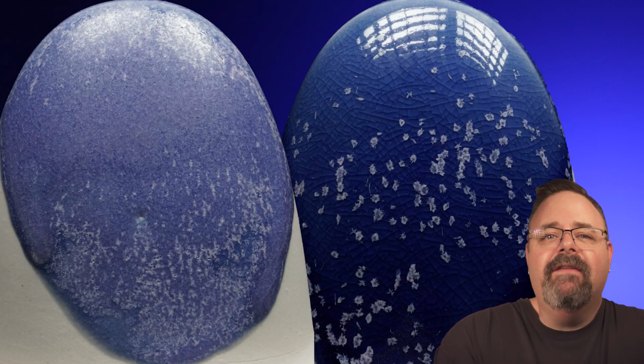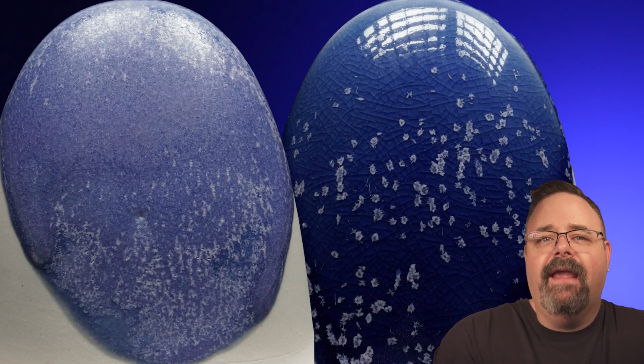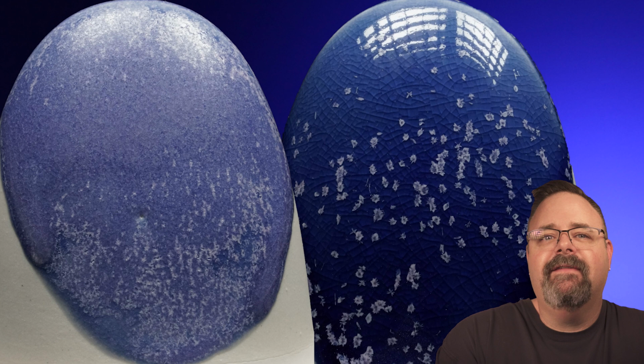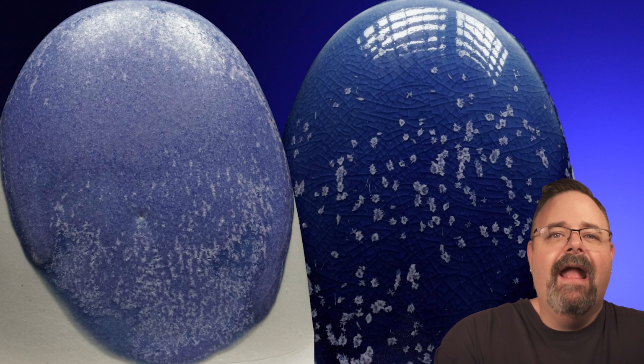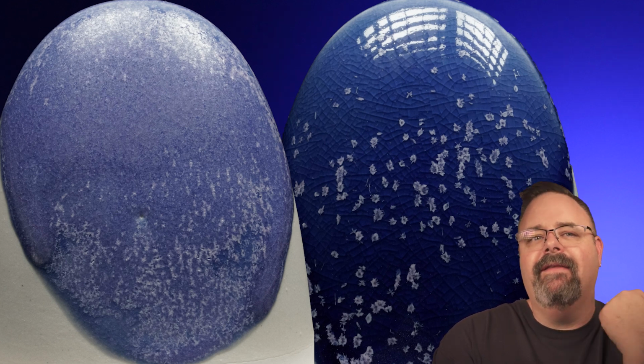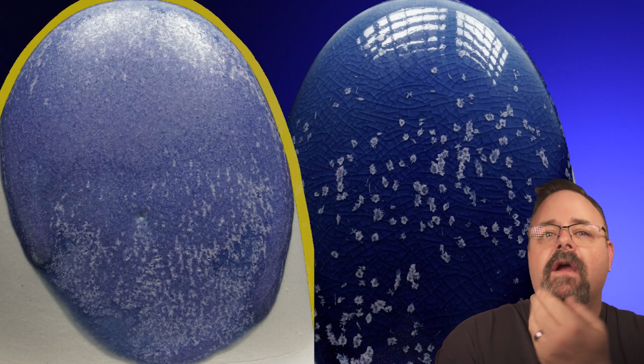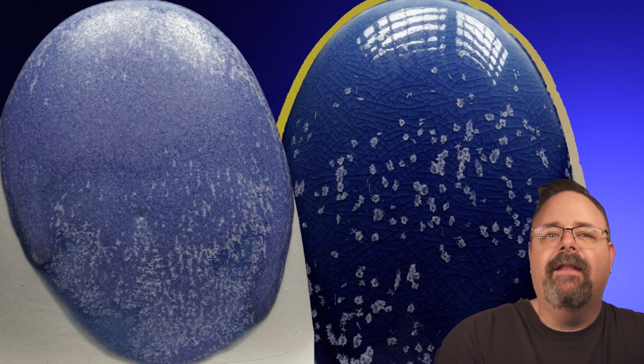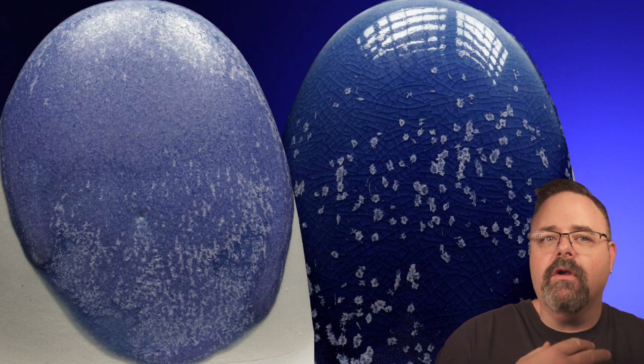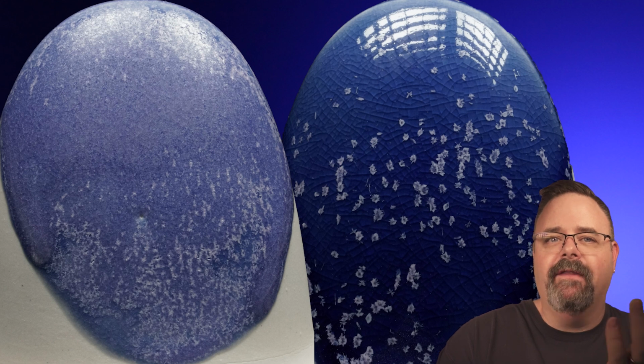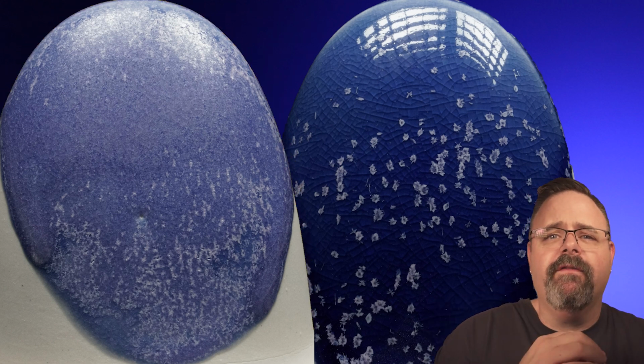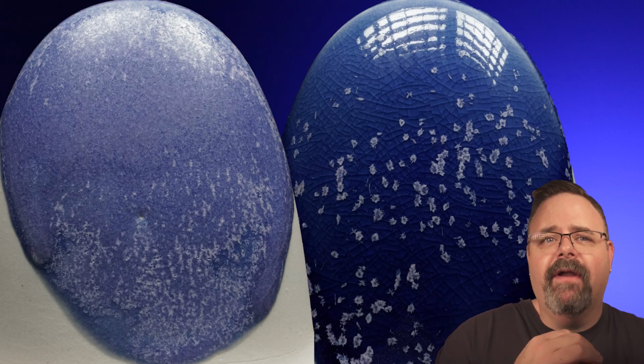And because of that, we can see behavior like this. These are the same glaze. This is a glaze in our glaze book, Test 7,500 glaze test, and this is a glaze of ours called Purple Rain. And this is what happens when the glaze gets fired a little bit cooler versus a little bit hotter. That the same glaze will make more crystals in the cooler firing on the left and fewer crystals in the hotter firing on the right.